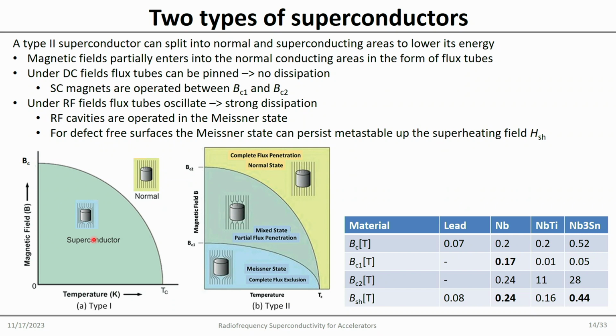They don't really like magnetic fields. So this is a plain, simple type 1 superconductor, just as mercury or lead. Basically all elements except for niobium. Niobium is a debate whether it's type 1 or type 2. It depends who you ask. This is the active region that we got. So basically as soon as you apply a field, it will get normal conducting.